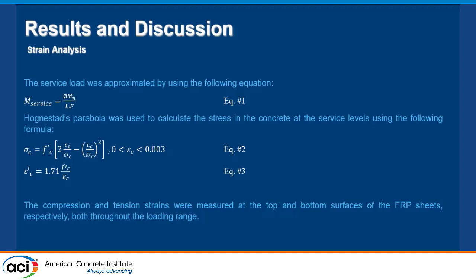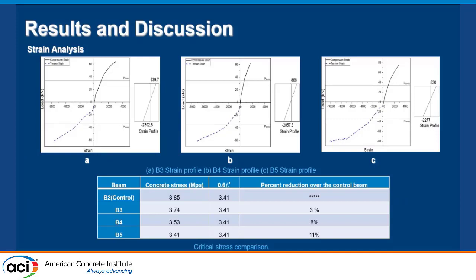So for the strain analysis that we did, we obtained the service moment by dividing by an average load factor, and then we used that to obtain the stress in the concrete using the Hognestad parabola. The strains in the concrete at the top, at the surface of the compression FRP, and at the tension were measured using the strain gauges that we added in the beams. And then we did the strain analysis. We found that this is the strain. So this table and the graph show that for beam 2, we have 3.41 as the 60% limit, and we are getting 3.85, which is higher.